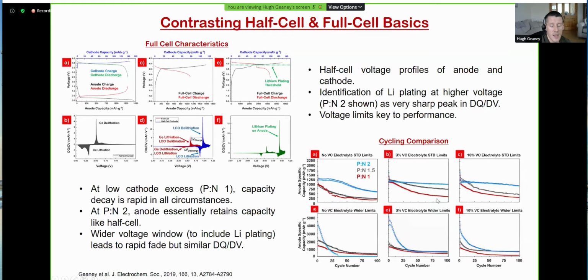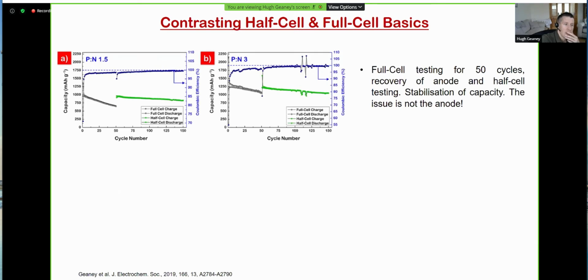Essentially what has happened is we have diminished some of that active lithium within the cell, and we started to lose capacity there. Again, there were some extra tests just to really hone in on the mechanisms that were going on. If we did a full cell charge, this was for a PN 1.5. This is full cell testing where I disassembled the anode afterwards and then put it back into a half cell. So this is with a fresh lithium metal, and what you'll see immediately is that the capacity returns to what you would expect it to be, and also the capacity retention is enhanced.